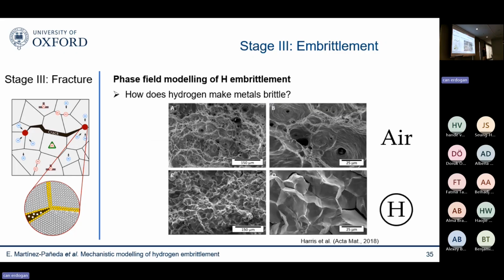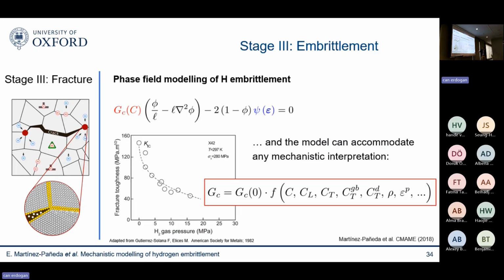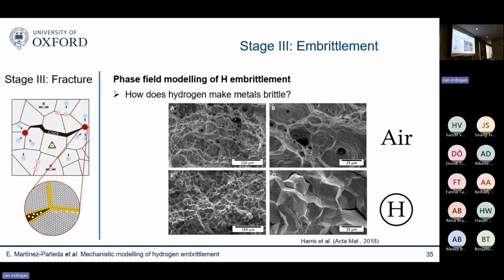And let me tell you what I think is happening. If you were to develop a mechanistic degradation function for hydrogen embrittlement, the key question to answer is how does hydrogen make metal break? How can it be that the same material, in the absence of hydrogen, fails in a very ductile fashion through micro void growth and coalescence mechanisms, and the moment you bring hydrogen into the picture, it fails in a very brittle way through, as you see here, intergranular cracking mechanisms? So what is happening between here?